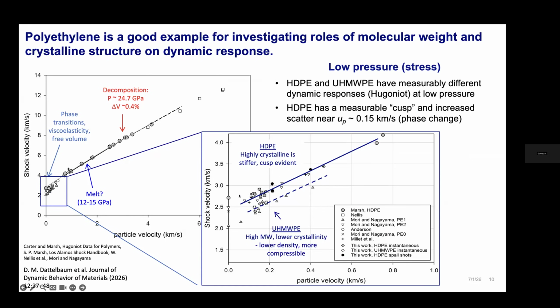But when you actually separate it by material, what you see is that the higher density polyethylene, the HDPE, lies higher in the Us-up plane, meaning it's less compressible than ultra high molecular weight. And almost universally, there's this cusp down here, which we believe is associated with a solid-solid phase transition. The magnitude of that cusp is strongly related to the amount of crystallinity in the polymer. This cusp is at about 0.15 kilometers a second, or 150 meters a second. And again, you don't extrapolate to the sound speed because you are compressing out a portion of that free volume associated with the amorphous domains.